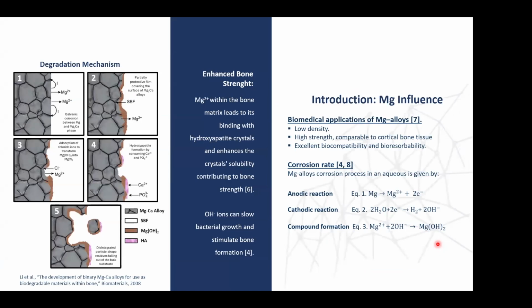So if we look at the mechanism for bioabsorbability, it is related at some point to the grain size. It starts usually with galvanic corrosion, but then some protective film is formed, mostly from the formation of magnesium hydroxide, and there is also some hydrogen evolution in this reaction. And then the formation of this film will interact very nicely with bone minerals like calcium ions or phosphate ions present in hydroxyapatite, which is the bone mineral.